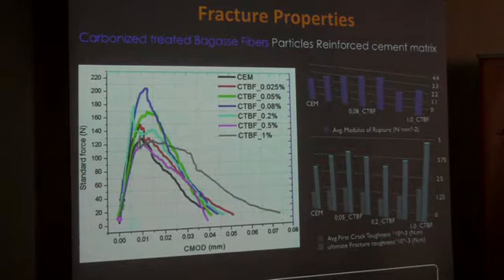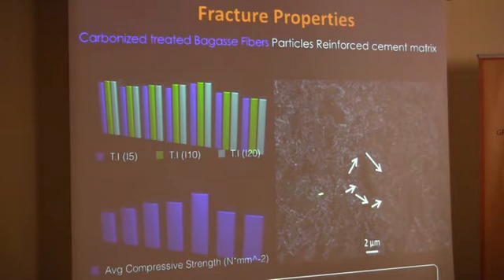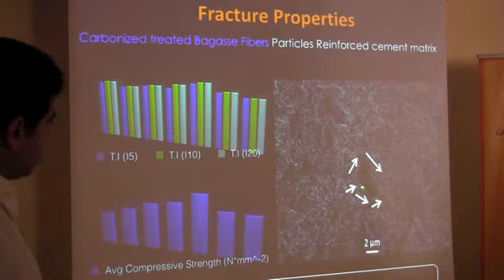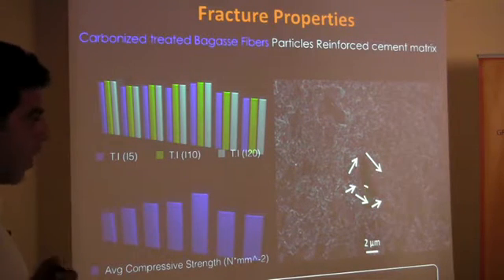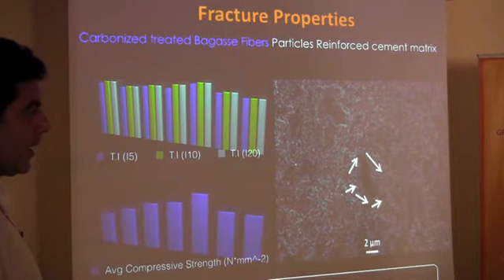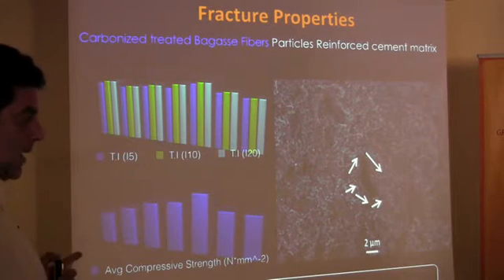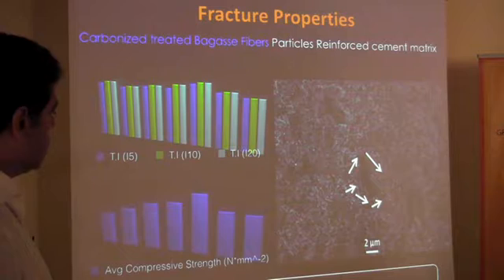In particular, when we add 0.08% in weight with respect to the cement, we obtain a very strong increment with respect to the stress, the resistance, but also we obtain an increment in ductility because it increases the fracture energy of the materials. Here there is a picture in which it's possible to understand why we obtain, of course, not only the increment in strength, but also the increment in ductility.